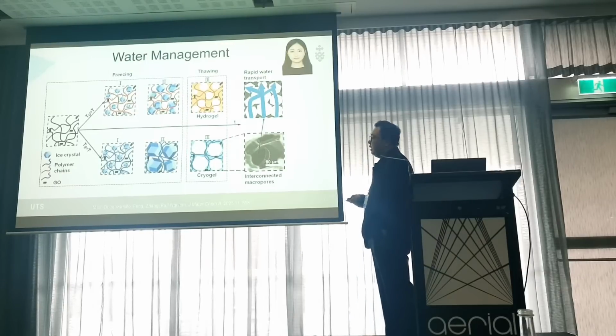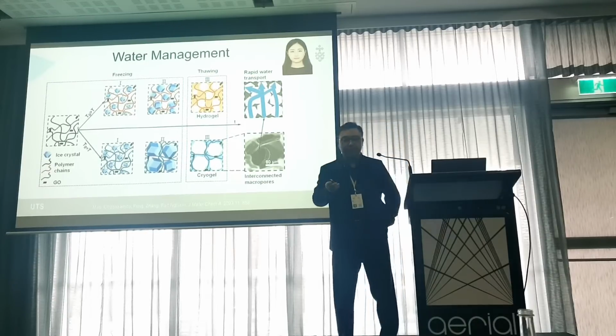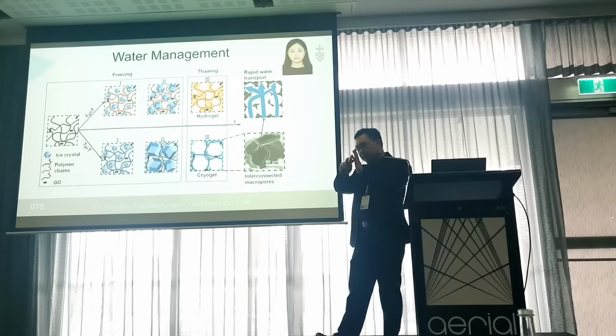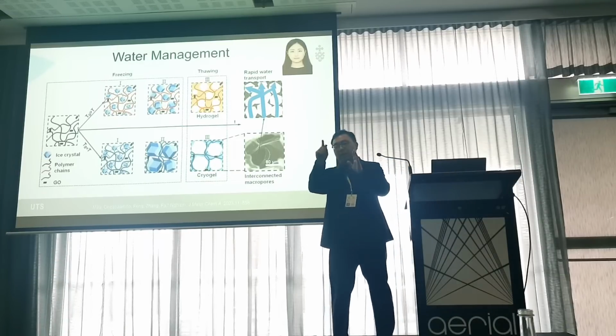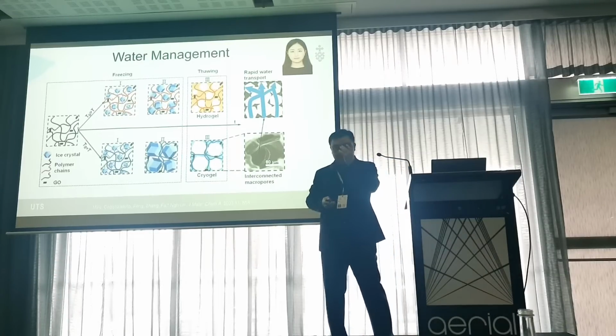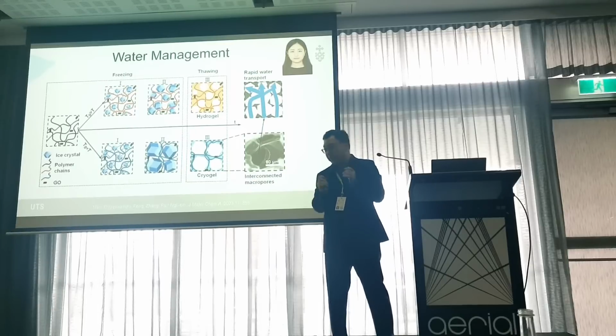This result can be attributed to the difference in the glass transition temperature between these raw materials. Specifically, the PVA has a higher Tg, about 50 degrees centigrade. So therefore, in the freezing process that's conducted at -18 degrees centigrade, the polymer chains lack flexibility.